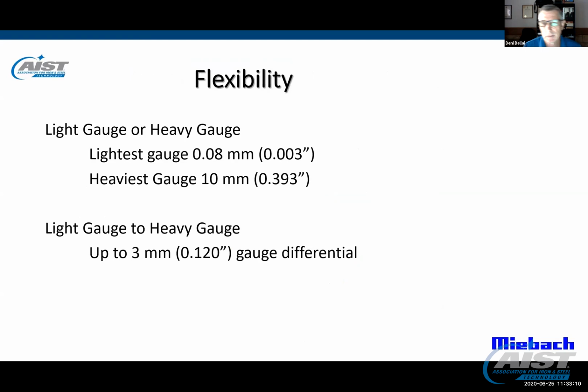Here we go. Flexibility. Laser welding can be used for very light gauge or heavy gauge products. The lightest gauge products that Miebach laser welders are capable of welding goes down to about 0.08 millimeters. That's about 3/1000ths of an inch. Other Miebach laser welders, and I can't speak for others, are working with materials up to 10 millimeters.